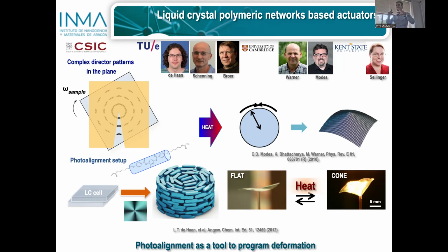We cannot make a circle smaller by increasing the radius. This can only happen if you go out of the plane and turn this into a cone, in which you can make the generatrix of the cone longer and the base smaller. So the system, to release the stresses, can escape into a cone. And actually, if you are indulgent with me, this is flat, not totally flat, but when you heat it up, then you get this cone. Later, we will see better ones. Okay, so this tells us that all these alignment techniques allow us to program the deformation of this system.